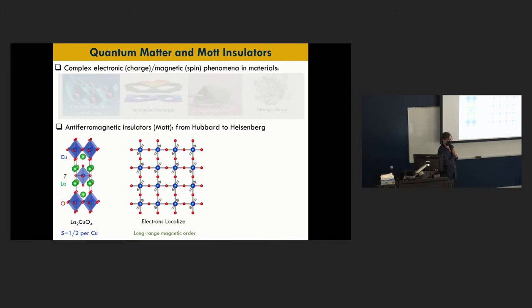So now, what do we have to do to understand this material? Well, we are left with one spin per site, and now we can start to understand how the spins interact with each other and how their excitations may behave in the system. And it turns out that the spin excitations are the lowest energy excitation in the system. This is what happens at low temperature in this system. And in particular, there is long-range magnetic order.